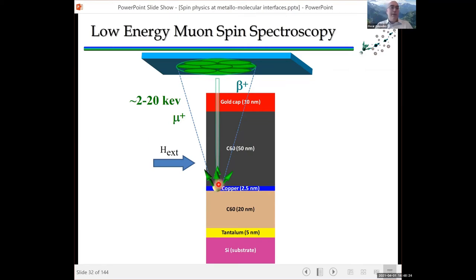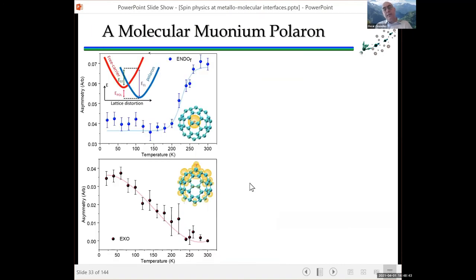So if you surround your samples by positron detectors, you will be able to see how your muons are oscillating in the local magnetic field generated at different depths in your sample. So it's a means of probing the magnetic information at different depths. In particular, in C60, the muons trap one of the electrons from C60 and form what is known as a muonium, which is the equivalent of a hydrogen atom, but with a muon instead of a proton and then an electron. And then that is going to couple with the vibrations of the molecule, to form what is known as a muonium polaron.